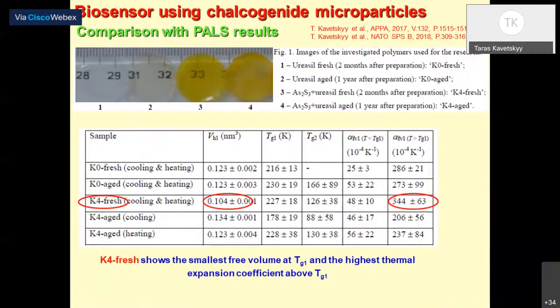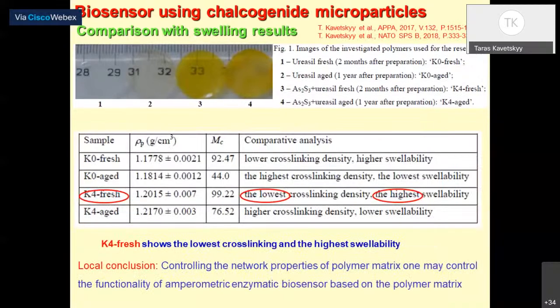Again, when we check the PALS parameters, we see that for this sample we have the larger changes in microscopic free volume, and also the highest swellability. So we made a local conclusion that we can control the network properties of the polymer matrix. Probably one may control the functionality of biosensors based on the polymer matrix.